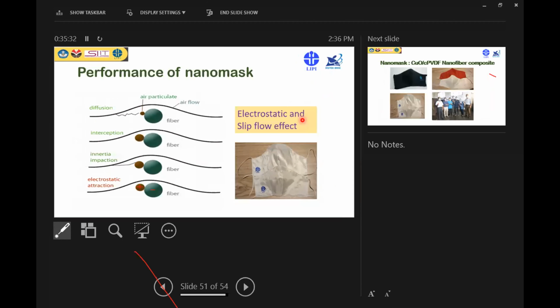We can explain this by this graph. You can see here, in the nano mask, the airflow is not zero at the fiber surface - this is the slip flow effect. But in the microfiber mask, the airflow rate is zero on the fiber surface.